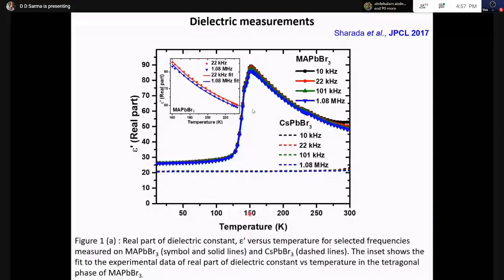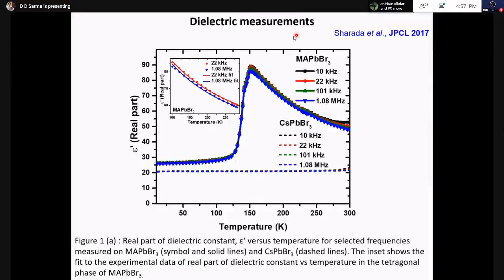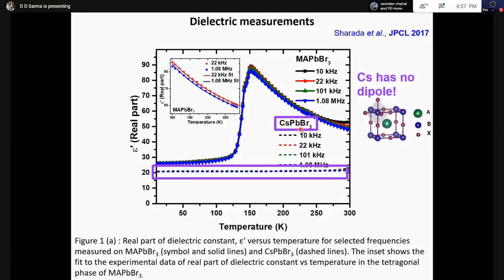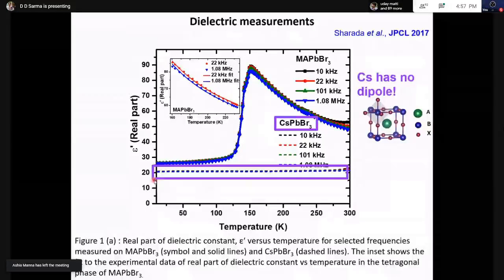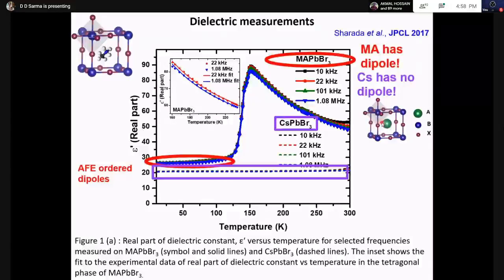It turns out that looking at the dielectric property gives us a clue. There's a very busy curve. I'll quickly walk you through stepwise. First, I want you to look at this particular part, which relates to CsPbBr3, whose structure is shown over here. The most important thing to note is that this MA that was at the bottom center position, I've put a cesium ion. So there is no dipole. And then the dielectric constant looks like this. So when dipoles don't contribute much to the dielectric constant, it looks like this. Now I'm going to replace that cesium with MAPbBr3. That's what I'm going to look at, and that is this one.